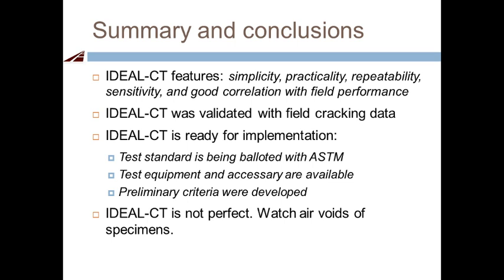If the question is about field cores, we haven't tested many field cores yet. If testing field cores, we recommend measuring the actual air voids before testing — that is very important. As mentioned, CT Index is sensitive to air void content: higher air voids give higher CT Index numbers.